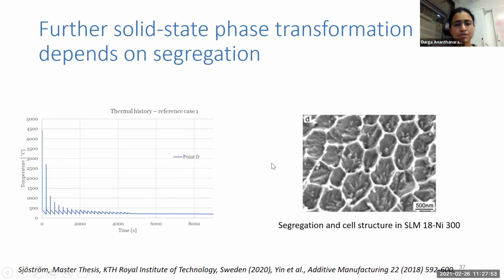So in order to do this, we also need to look at the segregation. This is an example from SLM 18 nickel 300, and this is part of the master thesis of Julia Sjöström, who worked in our group last year. She looked at the temperature evolution using this Simufact Additive software, so she had the whole thermal cycling that happens. We also found from literature that we have the cell structure and segregation in 18 nickel 300 as well.